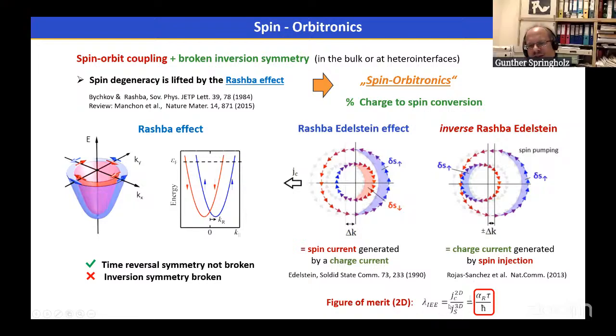So the figure of merit shown down here for a two-dimensional system is basically the ratio of the charge current to the spin current, and is proportional to the magnitude of the Rashba constant times the spin lifetime or spin scattering time. So that means to have a system with a large Rashba-Edelstein effect, you need a system with a very large Rashba coupling constant and a long spin scattering time, which randomizes the spin population.